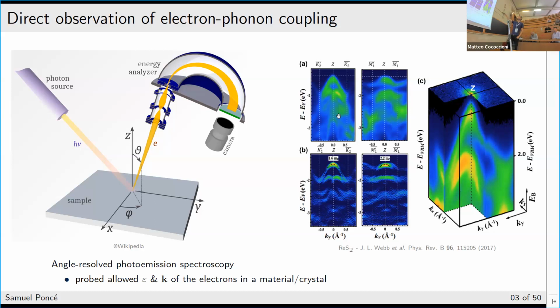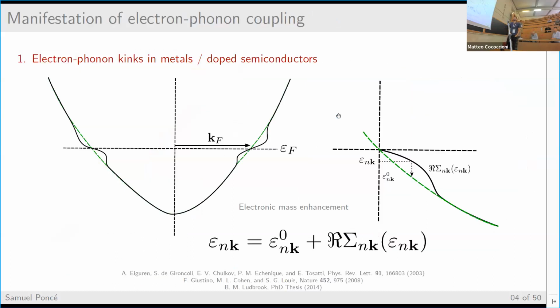What you notice is that the bands are not lines; they have a certain linewidth, and this linewidth is due to the lifetime of the quasi-particles. It is due to electron-phonon coupling, it is due to phonons. We will see that after the coffee break. But what is really nice is that this is maybe the most direct observation that we can make. And now, if we want to talk about electron-phonon coupling, I will show direct manifestations of that effect.